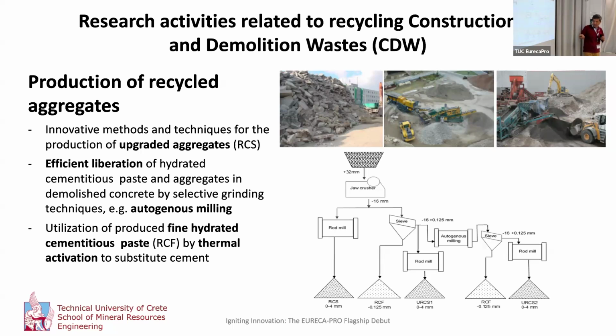So another research activity is to find a way to utilize this fine waste material, and one way we have proceeded up to now is by thermal activation, just heating at a temperature of around 600 degrees, and this material becomes again a kind of cement. So it can substitute a part of cement in mortars and concrete products.